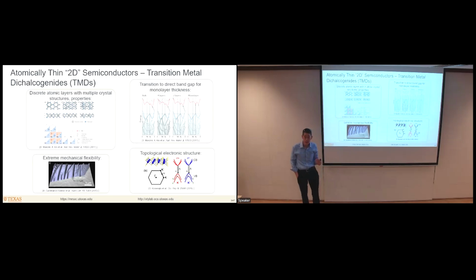As you get to this atomically thin limit, or maybe a few of these layers together, there are a number of very interesting properties that arise. One is that in this limit, the materials are extremely flexible mechanically, so you can have high levels of strain and very spatially inhomogeneous strain distributions. As one makes the transition from multi-layer material to monolayer material, there's also a transition in the electronic structure from having an indirect band gap for multi-layers to a direct band gap for monolayers. And that has major implications for the application of these materials in optoelectronic devices. There are also topological aspects to the electronic structure that arise.